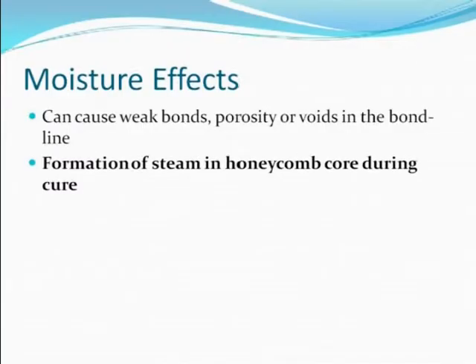I'd like to focus on one important aspect of handling composites in an uncured state: the damaging effects of absorbed moisture, which results in a dramatic reduction in strength. Reduced strength occurs with the presence of even a very small amount of moisture in prepregs or adhesives prior to curing the composite part.